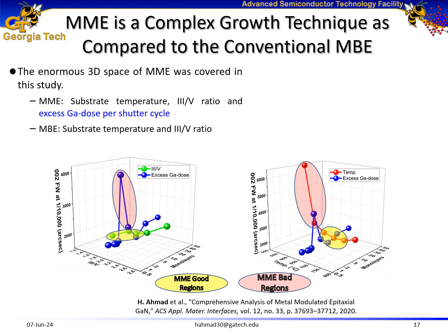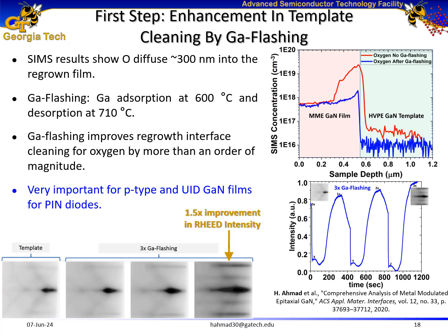In traditional MBE, the growth parameters are substrate temperature and III:V ratio. MME is more complex as compared to traditional MBE because in MME we also have an additional growth parameter, which is excess gallium dose per shutter cycle. So I wanted to study the effect of each growth parameter of MME on the quality of the films, but as a first step, I wanted to improve on the template cleaning.